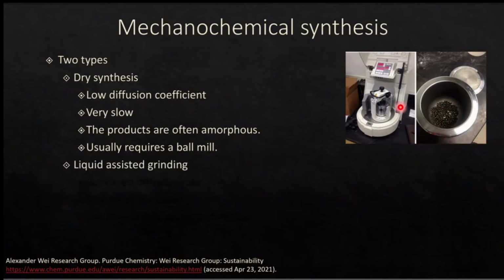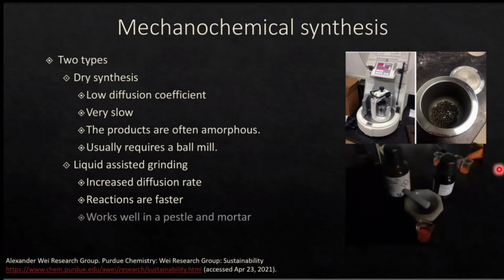Now we can also use liquid-assisted grinding in a ball mill. Then the idea would be to use just a small amount of solvent in order to increase the diffusion rate and make the reactions faster. This works well in a pestle and mortar as well, which is one of the benefits of using liquid-assisted grinding. And so the benefit of this is that you can do it with less expensive techniques, less expensive equipment, and you generally end up with a more crystalline sample because that liquid is still there to support the crystal formation.